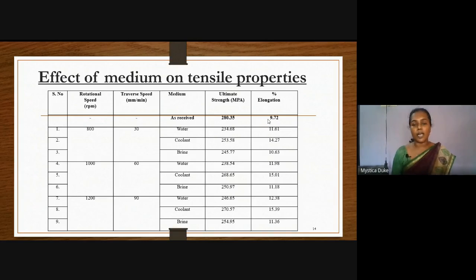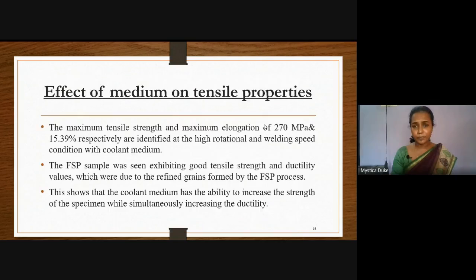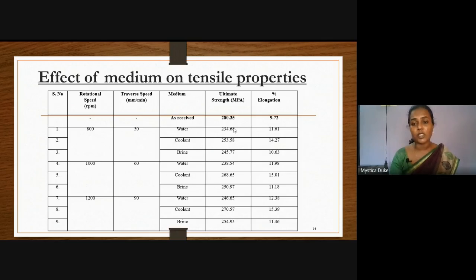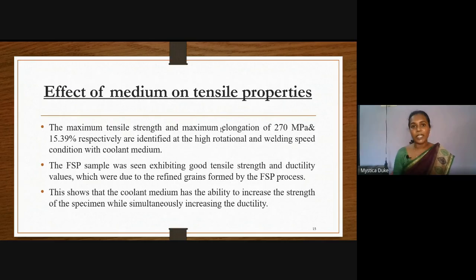So this actually proves that submerged friction stir processing of magnesium alloy improves the ductility, which was the main important objective of our study, because every combination produced better ductility. You can see that the ultimate strength is also maintained almost equal to the parent metal. This too is maintained simultaneously. This is mainly because of the ultra-fine grain structure that is developed by exposing the magnesium alloy to friction stir processing while submerging into different mediums.